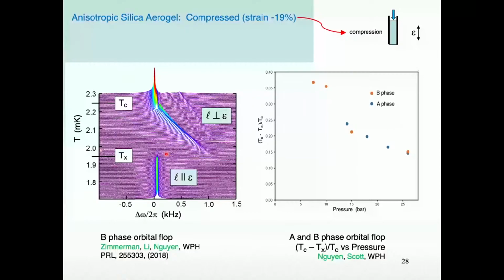And if you combine the Tx relative to Tc from both, you can see that they're rather consistent. So this is a measurement of the discrepancy of Tc minus Tx, normalized to Tc, as a function of pressure. And you can see that A phase and B phase are essentially identical. So this orbital flopping is consistent between the two, with one important exception. In the A phase, the angular momentum is parallel to the anisotropy axis close to Tc. And in the B phase, just the opposite, or 90 degrees with respect to that, it's parallel to the anisotropy axis at low temperatures. That's just the inversion of what you have in the A phase, and that's a very interesting phenomenon.